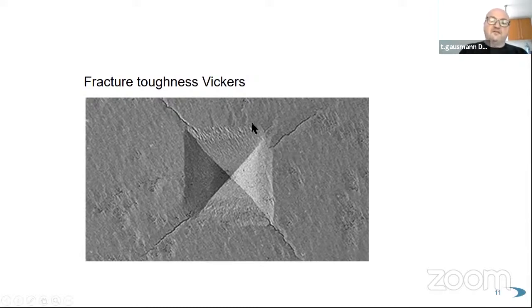So this is the Vickers test. You press a pyramid of diamond into the material, and then at the ends of the diamond, you get cracks in the zirconium material. And these marketing guys from other companies said, this is a brilliant idea. What we do is we measure these lengths, and then we have a quality.